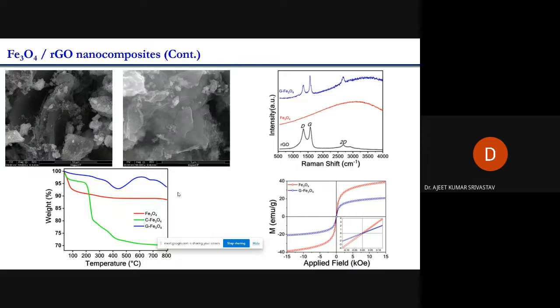And on the right side, coming to the Raman spectroscopic data, you can see that the behavior of the graphene, the layered structure, is not changed. That is the first thing. Second, the superparamagnetic behavior of the particles was retained. If you see the bottom right figure, the hysteresis loop has been shown. So it means the nanocomposites were realized without any change in the individual components, in terms of properties and physical appearance.